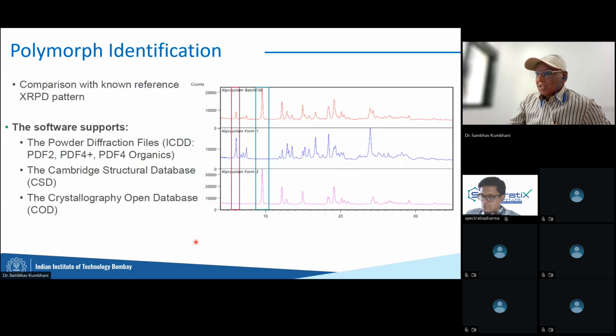So here's a real-world example from pharma. This is an alprazolam tablet form. It has two polymorphs, morph 1 and morph 2, for example. This is the actual batch that was produced, and they are confirming which polymorph is dominant in it. You can very clearly see that if it was polymorph 1, this should have been a much bigger peak than what you have here. Versus you can clearly see this is a matching peak to form 2. Similarly, you can go through the entire spectra and compare it like that.